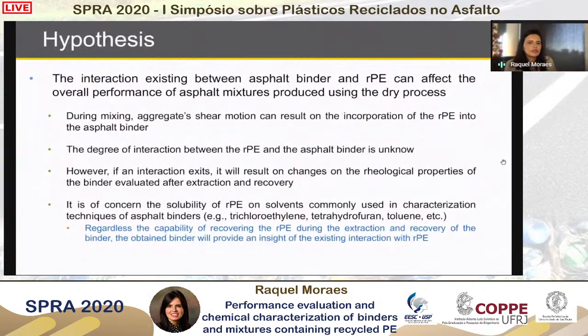The hypothesis that we had is that the interaction existing between the asphalt binder and the recycled plastic can affect the overall performance of the mixture, even though it is constructed using the dry process. And the whole hypothesis would be that during mixing, the aggregate shear motion will result in the incorporation of the recycled plastic into the asphalt binder. And this degree of interaction is unknown. But if an interaction exists, it will result in a change in the rheological properties of the binder that could be captured after the extraction and recovery.